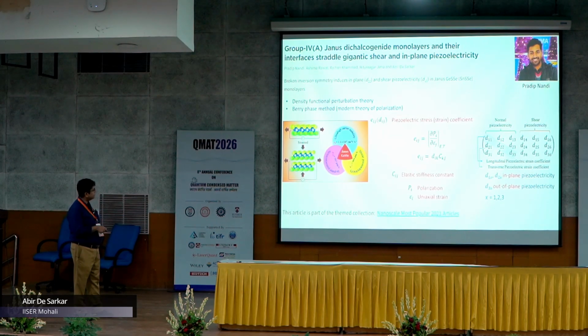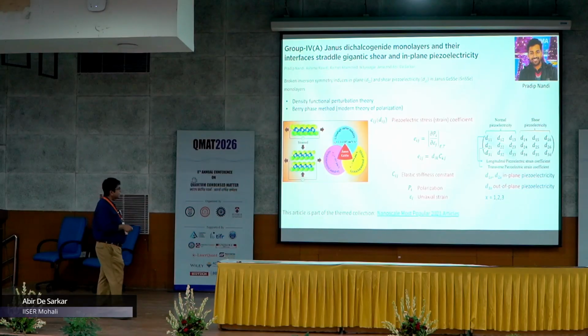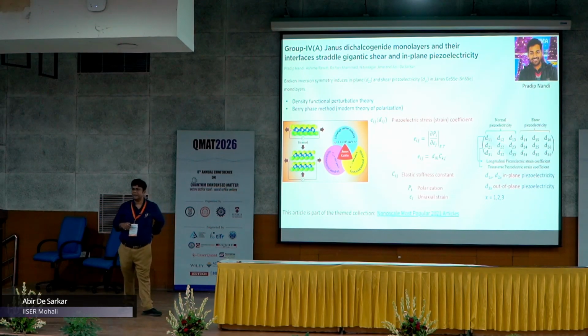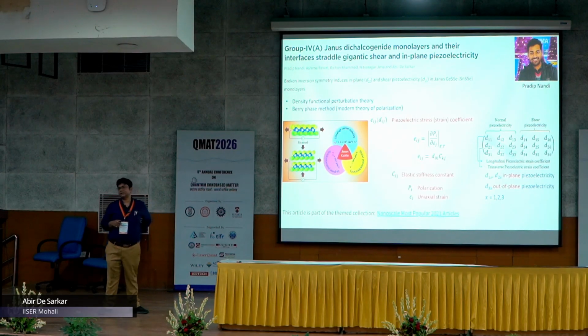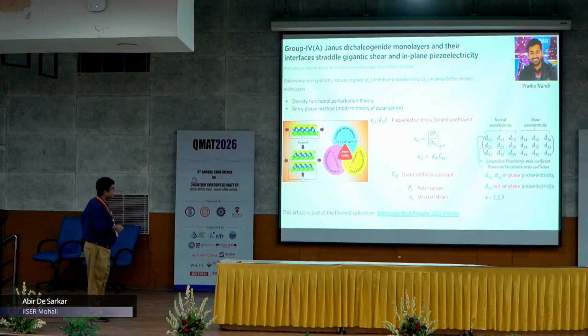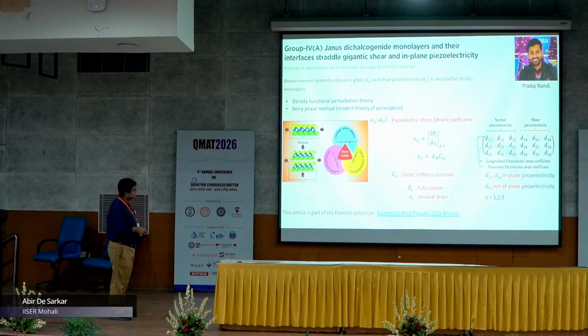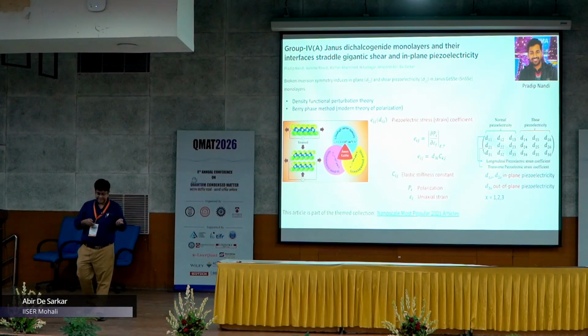The piezoelectric stress and strain coefficients are linked to each other through the elastic stiffness constant, and the piezoelectric strain coefficients are experimentally measurable. So finally we compute the piezoelectric stress and strain coefficients, that is, these tensor components. If you pay attention to the first two rows under normal piezoelectricity, they represent the in-plane piezoelectricity, while the last row corresponds to the out-of-plane piezoelectricity.